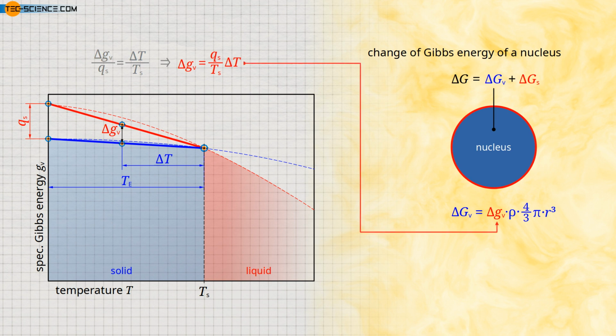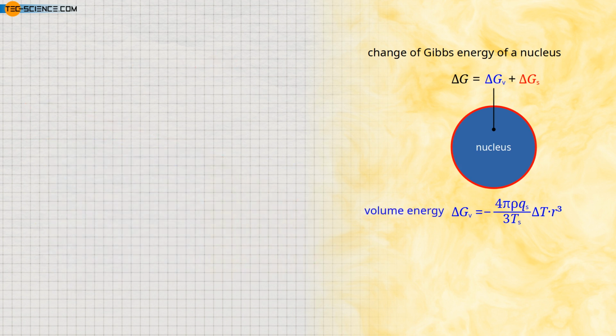We now use this expression in our original equation. Overall, this gives the given equation for calculating the change in Gibbs energy when a nucleus of radius r forms at supercooling delta T. Since it is common to state the supercooling delta T as a positive value, we introduce a negative sign at this point because, as explained earlier, the Gibbs energy of the solid state is lower than that of the liquid state when supercooled. Note that the Gibbs energy term just derived refers only to the energy content of the nucleus volume. One could therefore also speak of the volume energy.